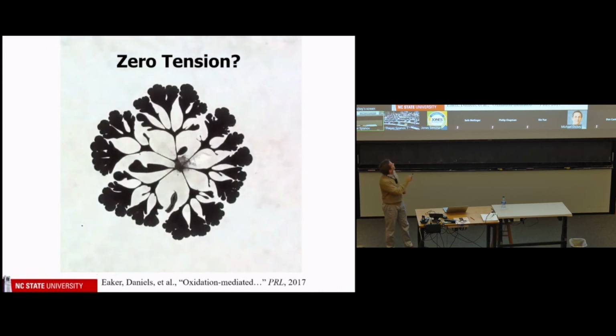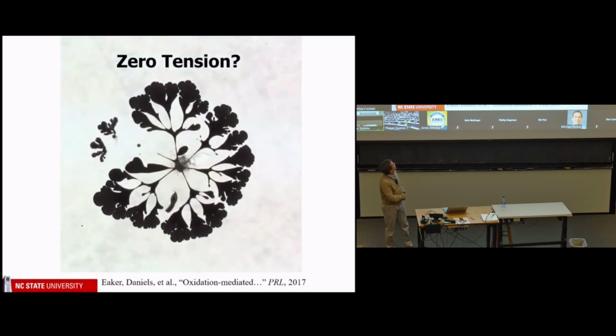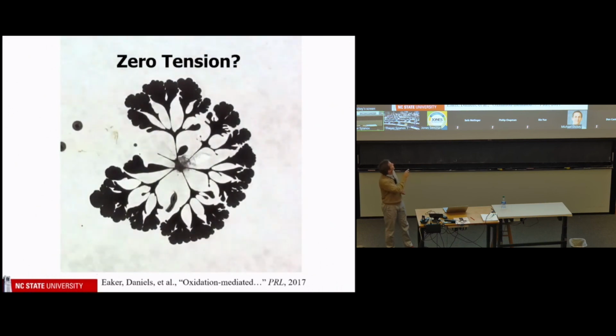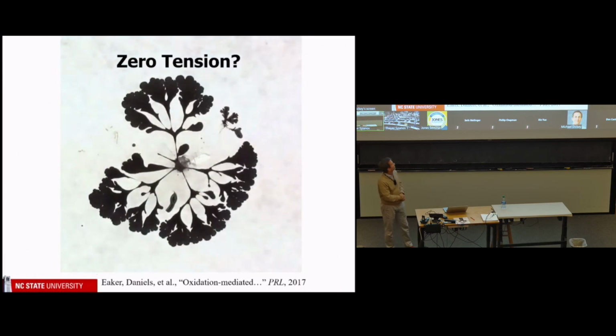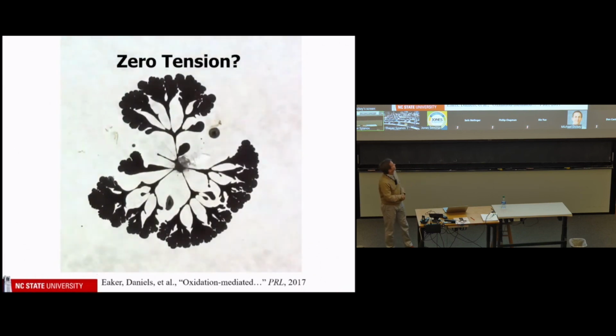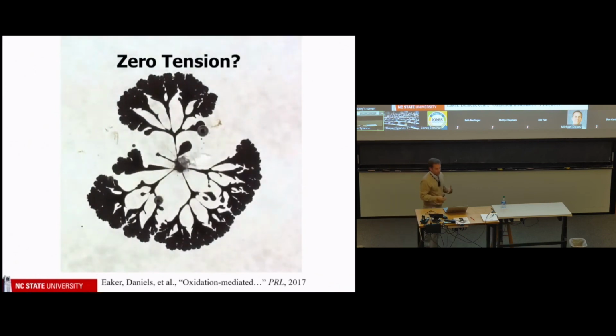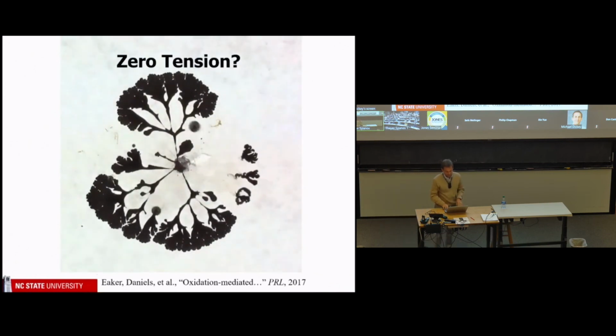And you'll notice that occasionally these little things will break off, and when they do, whatever was on the surface goes away because it's in the sodium hydroxide, and it just beads back up because it's got high surface tension. So we're kind of taming the beast with less than a volt. It's actually 0.8 volts.